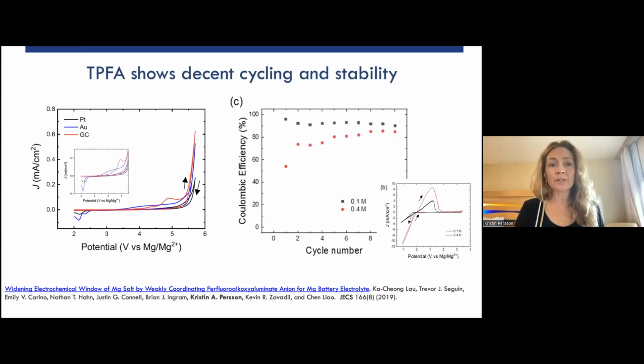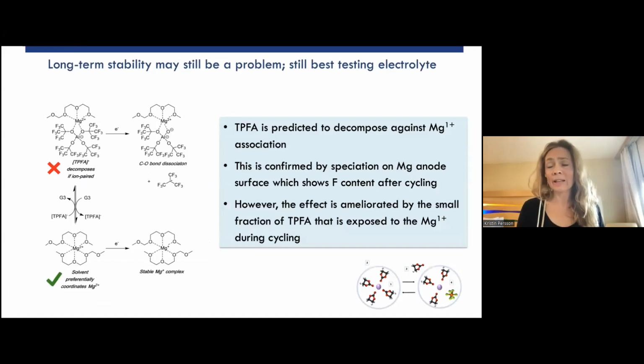And indeed, you can see here from the Coulombic measurements that it does show quite decent cycling and stability. It's not perfect, and we think we know why. This goes back to what I originally started with: even if you have a highly weakly coordinated anion, the very small amounts of TPFA that will be contact ion paired, because there has to be some in any chemical equilibrium, will be unstable when it's exposed to the plating conditions.